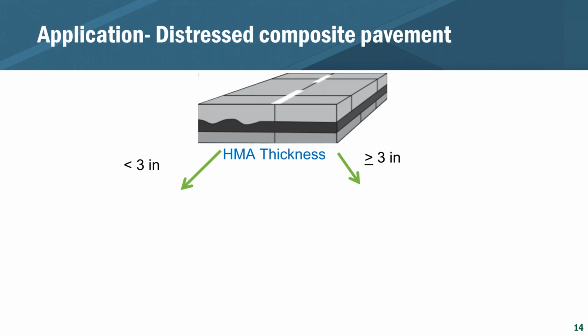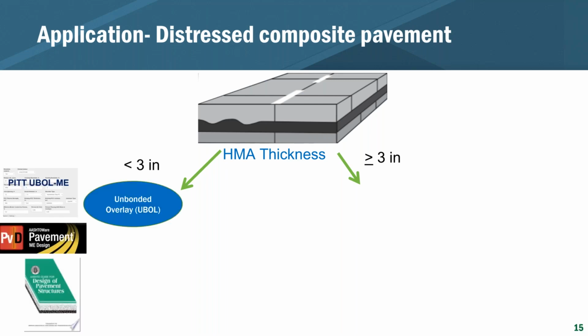And 3 inches is kind of your intermediate area, which you're probably going to go both ways, because typically if you're going to have an asphalt interlayer, so a composite pavement, you're going to mill the asphalt down to the thickness of the interlayer, and then you'll have maybe 1 to 2 inches. Some people leave up to 3. You get much more than that, and it's going to be responding a little bit differently. So if it's less than 3 inches, then that's going to create a slip plane, and you're going to design it as an unbonded. And we'll talk a little bit more about that in a future webinar.